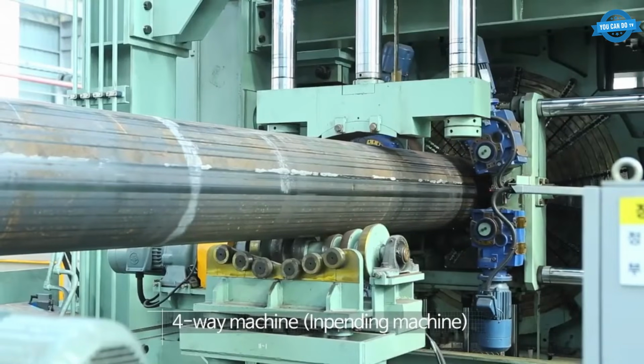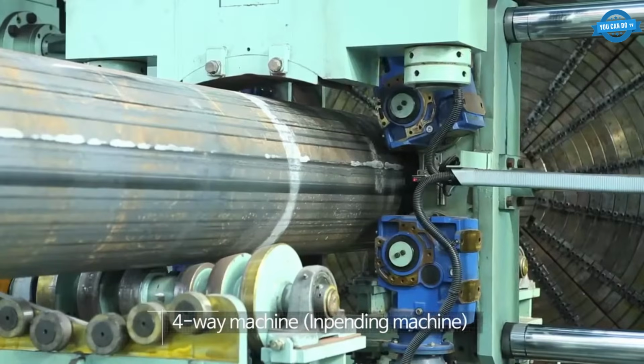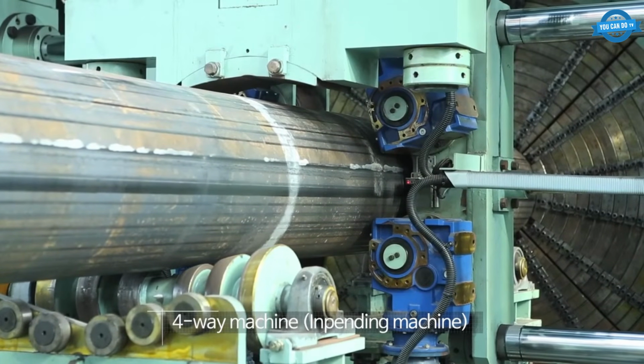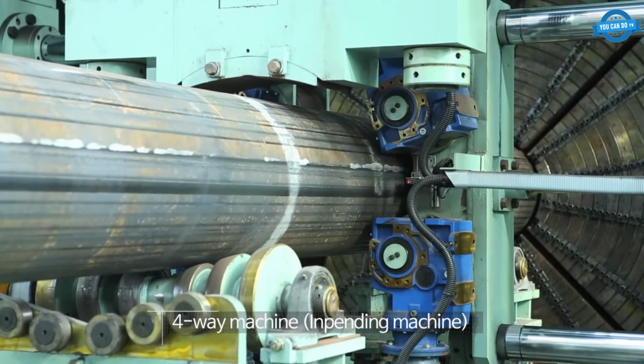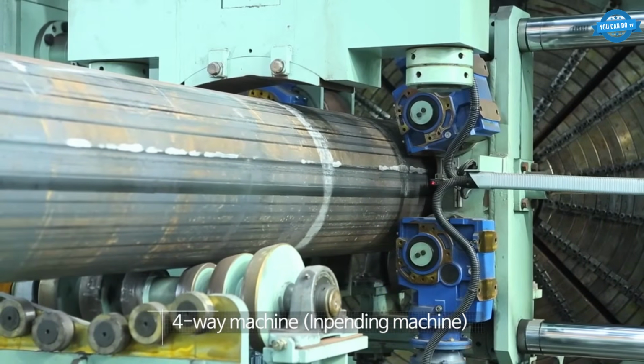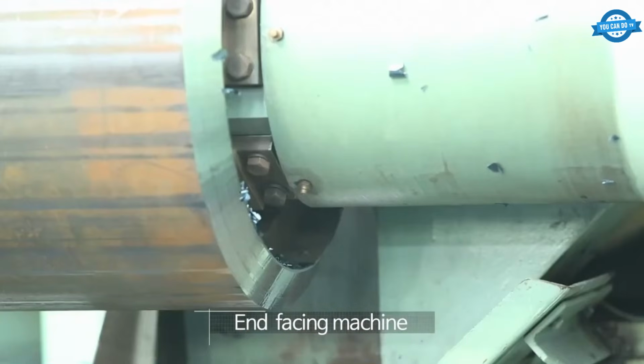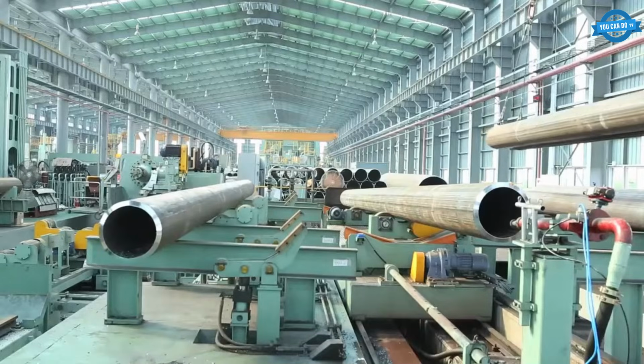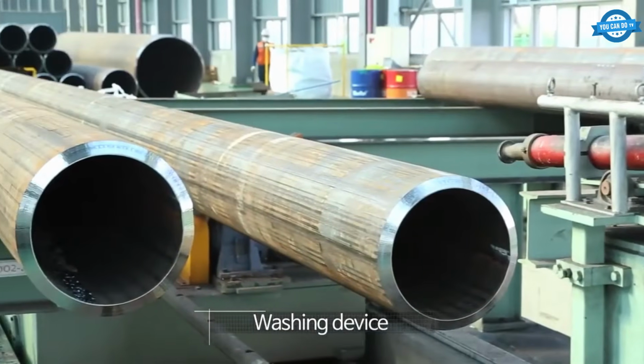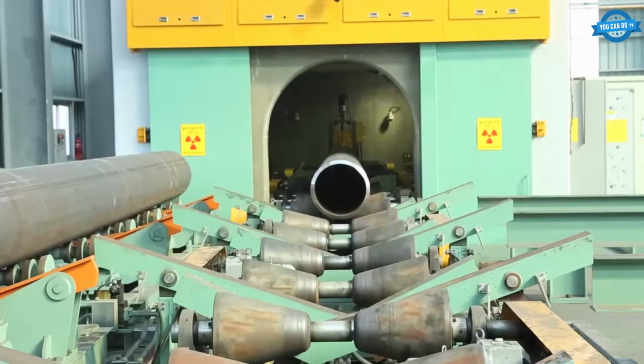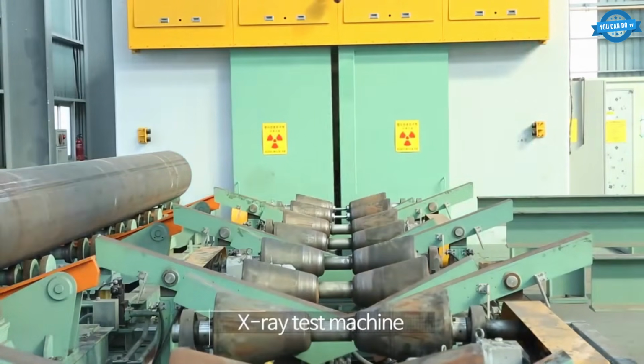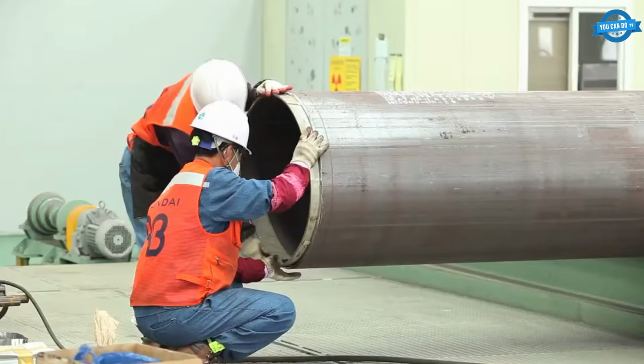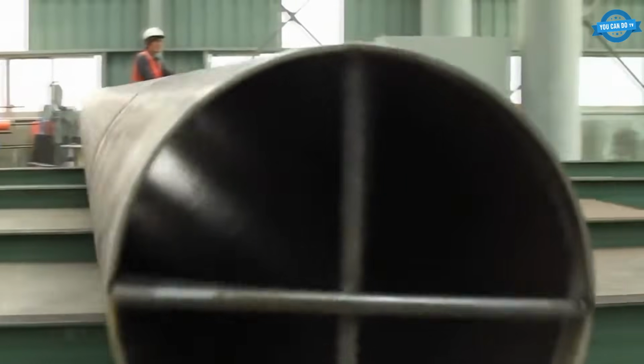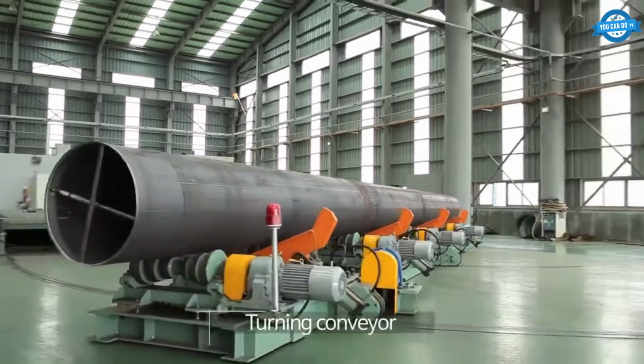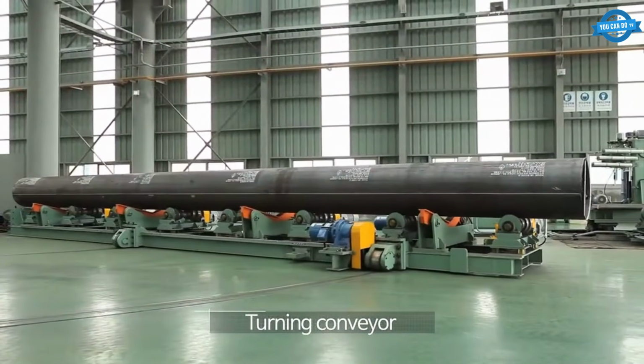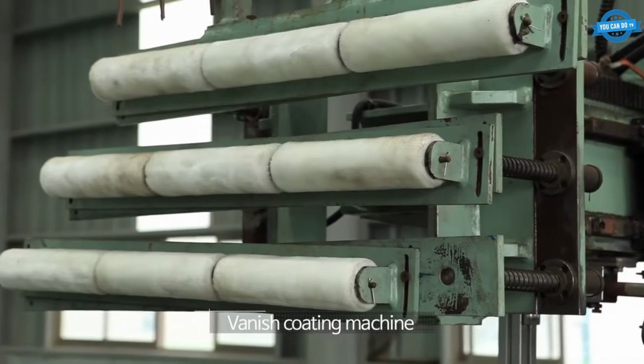Once welded, the pipe moves through a four-way expander that presses the cross-section into final calibration, correcting any ovality left by the forming process. An end-facing machine chamfers both open ends to prepare them for field welding later. A washing device cleans residue from inside and outside surfaces. An X-ray testing machine scans the full length of the seam under radiation shielding, verifying internal integrity before the pipe is cleared. A varnish coating machine applies an initial protective layer.